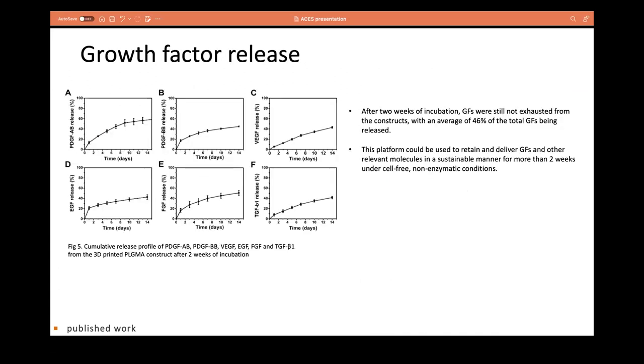Moving on to the growth factor release. Platelet lysate contains a large number of bioactive proteins, many of which have a fundamental role in homeostasis and tissue remodeling. In this study, six different growth factors were used as an indicator of multiple factors and biologically relevant molecules present in the platelet lysate. The cumulative release profile of those growth factors indicates that after 2 weeks of incubation, growth factors were still not exhausted from the printed constructs, showing the potential of the platform to be used as a long-term delivery system for growth factors.